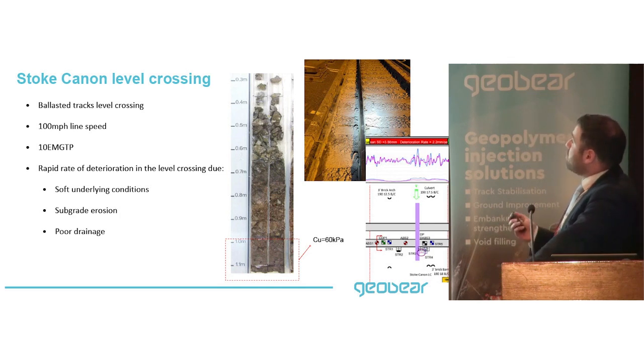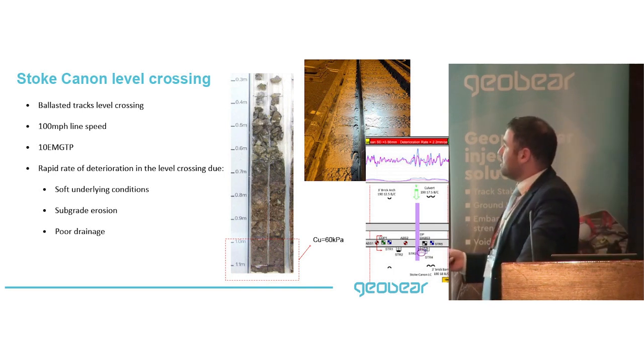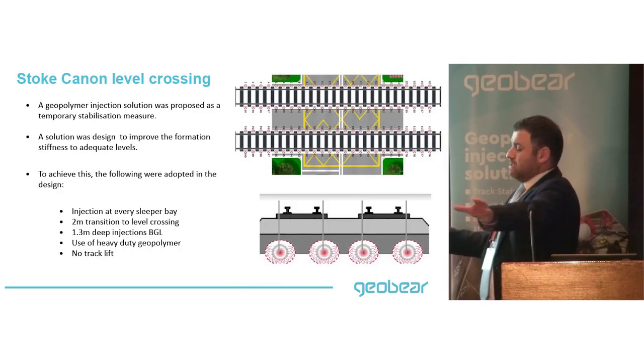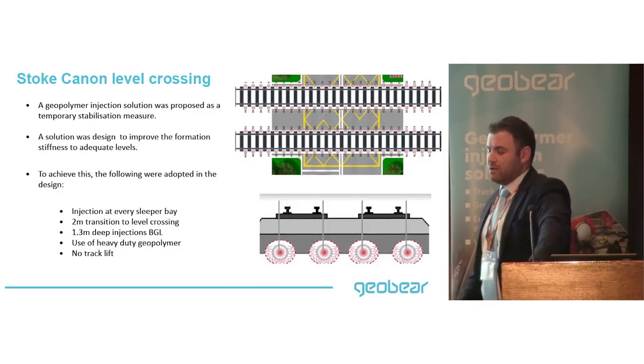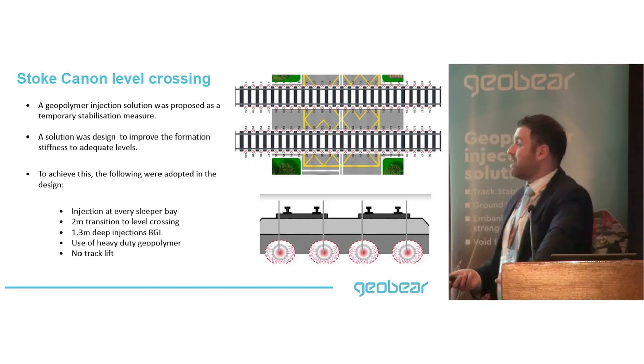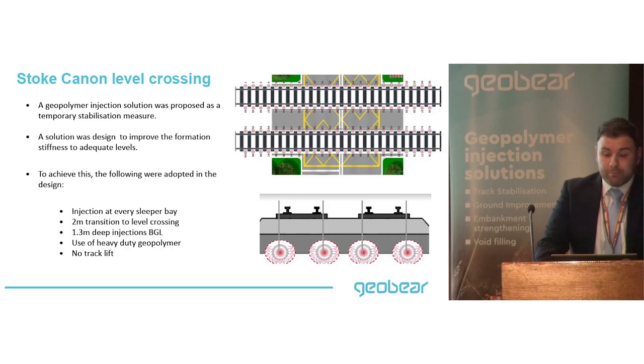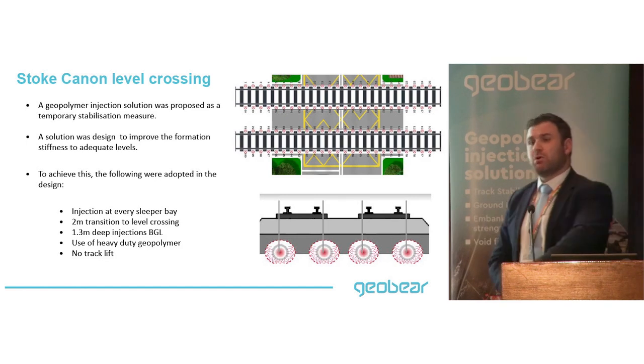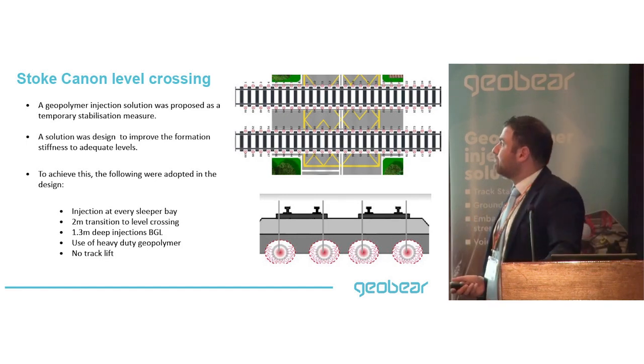So far we've completed the down line, and we're supposed to complete the up line. What we've done is inject right below the sleepers at a depth of 1.3 meters, and extended the treatment about 2 meters each side of the level crossing to create a transition zone, using a very heavy-duty, high-density geopolymer. One of the main objectives was that we should not create any track heave or lift, so we had very rigorous monitoring to make sure that didn't happen.